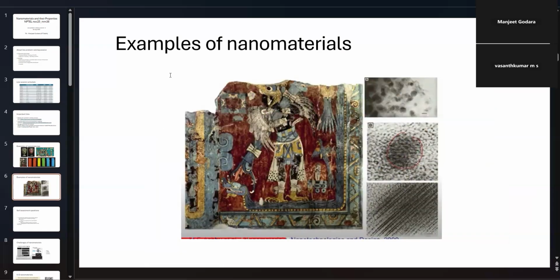So here, for example, of nanoparticle. In the paint, you can see these distinct small particles in the high resolution transmission electron microscopy images. This is a single particle, again in nanometer range, which gives this distinct yellow color. And because this is made of nanoparticles, the color doesn't degrade and is maintained over a much longer duration. If you use organic dyes or organic compounds, they eventually over time deteriorate and lose the color.